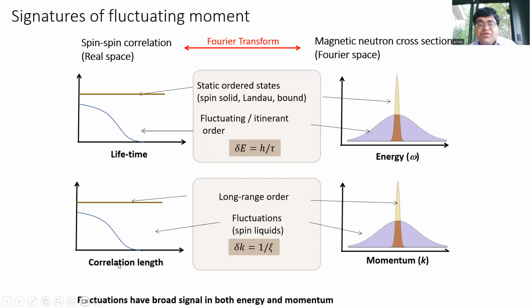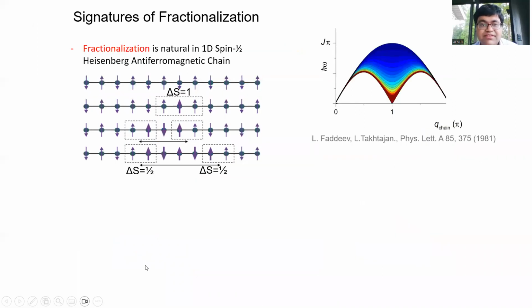The same thing is true for correlation length. If the correlation length is long, you get very sharp Bragg peaks, very sharp peaks in Fourier space. If the correlation length is short, you get very broad features in your momentum space. Same for lifetime. If your lifetime is long, you get very sharp features in energy space. If your lifetimes are short, you get very broad features. This is something we constantly look for when we do this scattering analysis. Short lifetime and short correlation length is a telltale signature of a fluctuating moment.